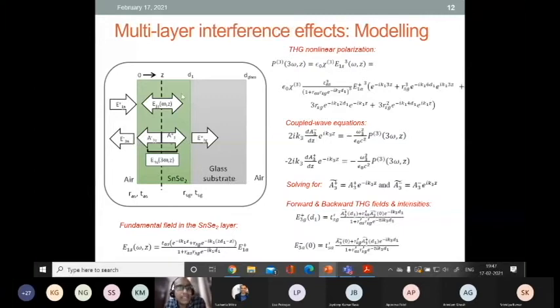And one thing which is striking is that the refractive index of these layers, right? This could be just tens of nanometers thick, but the refractive index of this media is very high, about 3.5. And for some TMDCs, it's been reported as high as 4 or 4.5 as well. So one could expect a strong standing wave type pattern to be set up inside this cavity. You can think of it as a miniature cavity where there is a standing wave. So there are fundamental fields, or the pump fields, which are propagating both in the forward and the backward directions, which need to be accounted for if you want to model the nonlinear signal generation. So that's what we have done in detail.